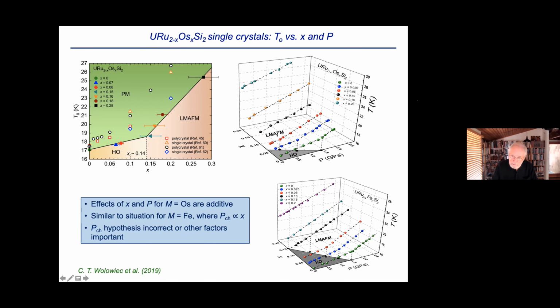And then for osmium, you find kinks in the phase boundaries. So this is pure URu2Si2. And then when you put in some osmium, the kink occurs at lower pressure. And that just evolves as you add more and more osmium. So again, you generate a plane of osmium composition and pressure within which the hidden order phase occurs. And then outside of it, you get a large moment antiferromagnetic phase. Okay, so again, you get this additivity of the tuning parameters, pressure and osmium concentration, when you tune the transition using these two mechanisms.